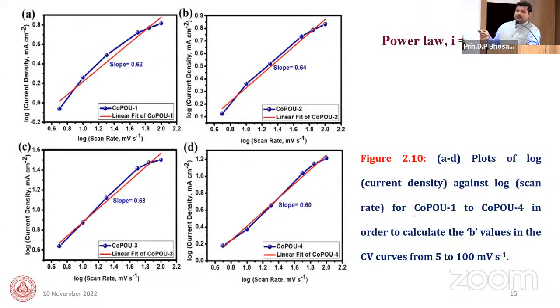Then I studied the capacity contribution and battery type contribution of the material. In this study, we calculated the B value using the power law. If the B value is 0.5, it is called battery type behavior, and if the B value is 1, it is called pseudo capacitive behavior. In our case, the B value is between 0.5 and 1, so this is 0.62, 0.64, 0.68, something like that. So in our case, the material shows both pseudo capacitive and battery type behavior.